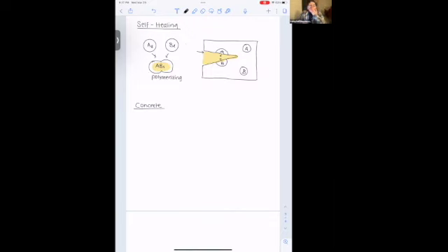And it can seal cracks up to 300 micrometers. But we can improve that with different other strategies. And so we want to use autonomous self-healing, which is just using chemical or biological reagents embedded within the material that are released when the cracking occurs.